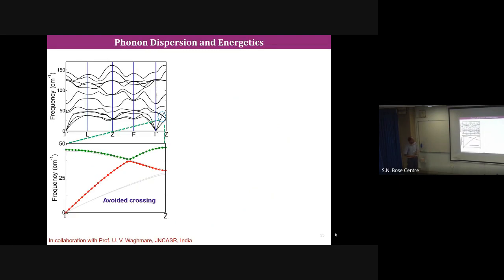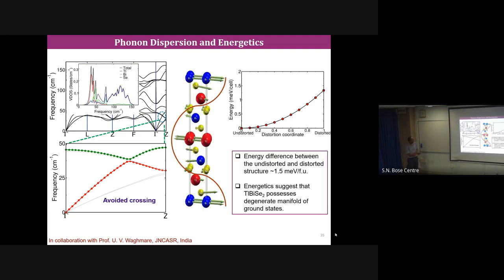And then Umesh has calculated the phonon. You see these three acoustic modes, but very low energy optical modes, which actually have an avoided crossing. And this feature is very important to have low thermal conductivity. This is the avoided crossing feature. And then from the eigenmode visualization of a low energy mode, this 50 centimeter inverse mode, you can see that this is simple shearing. Thallium and bismuth show this kind of shearing behavior. So that tells that what we showed in the experiment is validated by theoretical calculation.